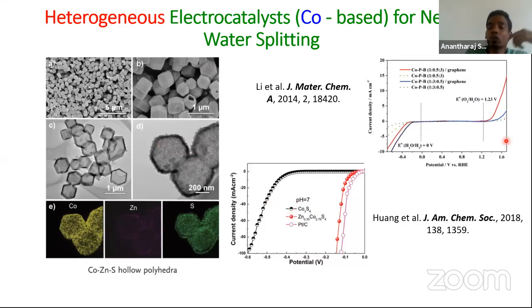And here I have shown another example, where you can see cobalt. This is actually a cobalt phosphate borate complex, which was used to generate both hydrogen and oxygen. They found that cobalt phosphate borate with this ratio delivered better HER activity, but when the ratio is like this, it delivered better activity for OER. So just by tuning the anion and the anion to metal ratio, you can also play with the activity.